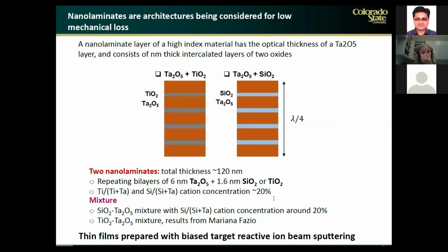So we prepared two nanolaminates, one of tantalum and titanium and the other one of tantalum and silica. The thickness of these nanolaminates is typically selected to be quarter wave at 1064 nanometers. Again, we use the sputtering method that I described at the beginning. And because we have these very low sputtering rates, we can actually create very well-defined nanolaminates.